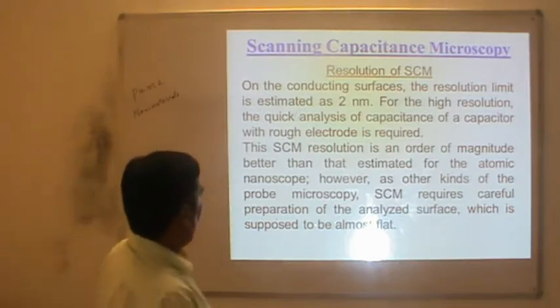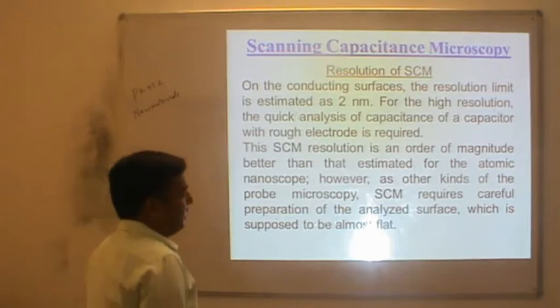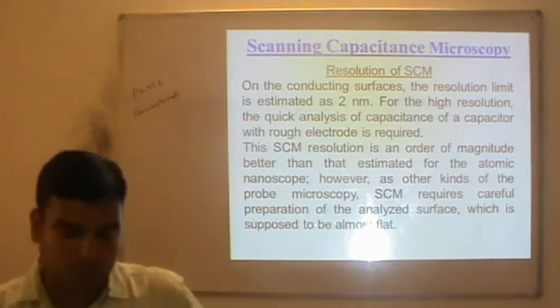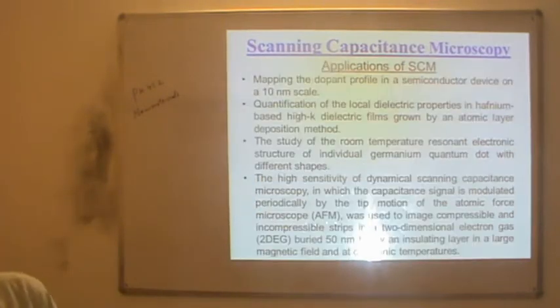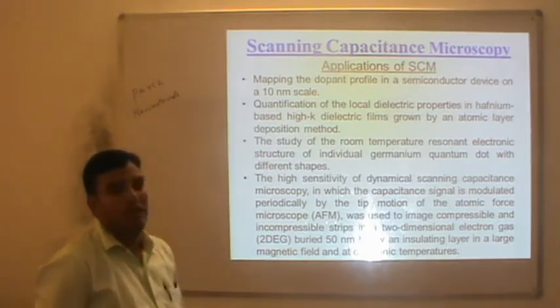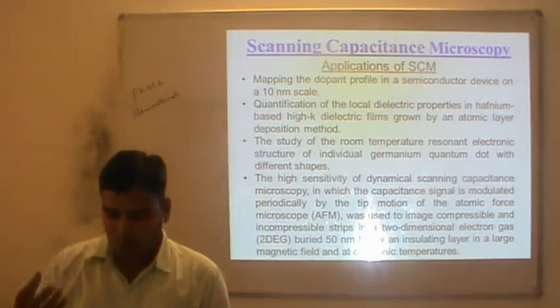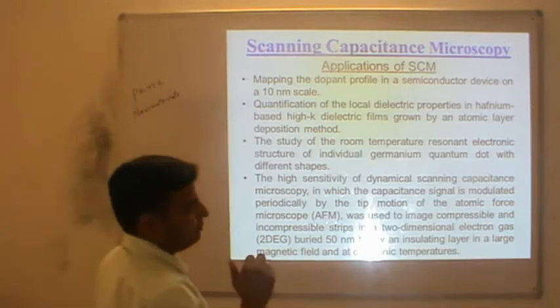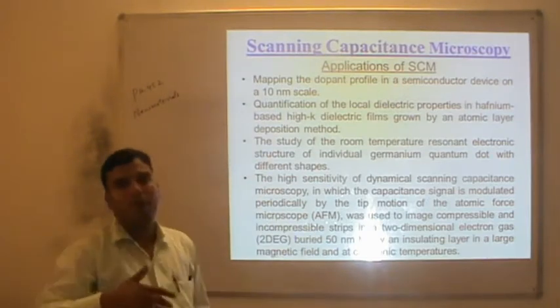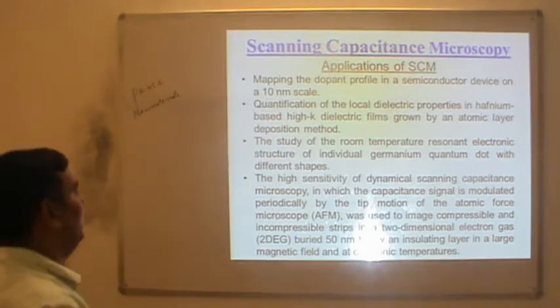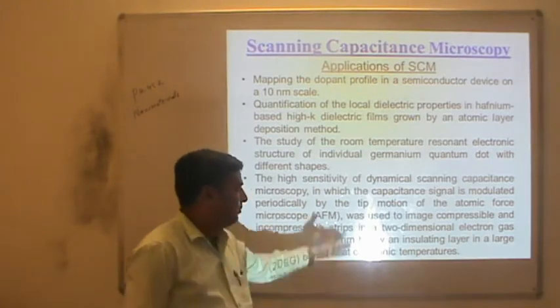This resolution is an order of magnitude better than that estimated for atomic nanoscopes. However, SCM requires precise preparation of the analyzed surface, which must be almost flat — as discussed for AFM, sample preparation is the most important parameter for all scanning probe microscopy. The applications of SCM include mapping the doping profile in semiconducting devices at 10 nm scale, quantification of local dielectric properties, and characterizing high-k dielectric films grown by atomic layer deposition.